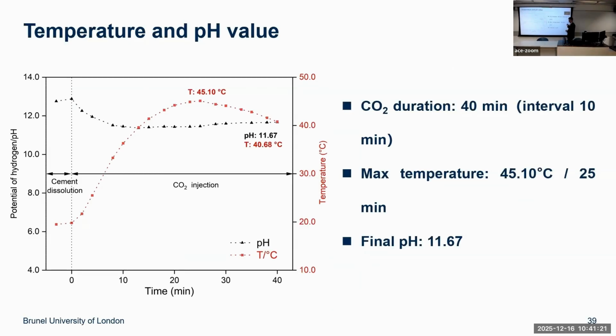As mentioned, we're trying to reduce the time needed for the whole process to around half an hour. This is our target. We use CO2 injection for 10 minutes, 20 minutes, 30 minutes, and 40 minutes. That's what we did in the lab, and we measured pH and temperature, which is a way to track the hydration. Finally, we found the highest temperature is around 25 minutes at 45 degrees.